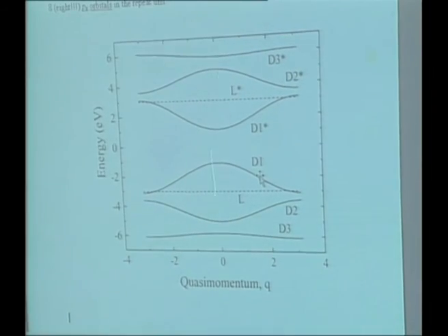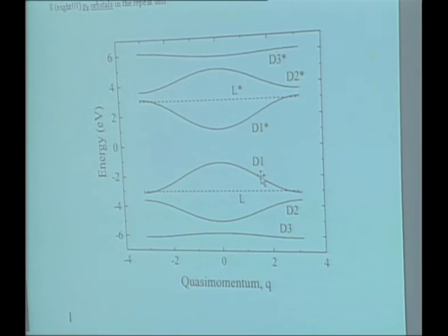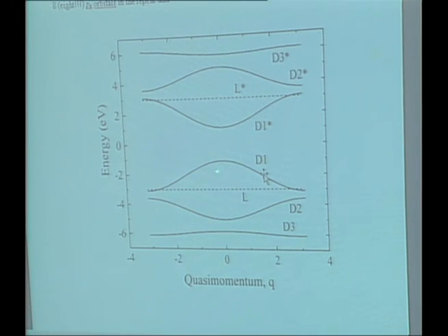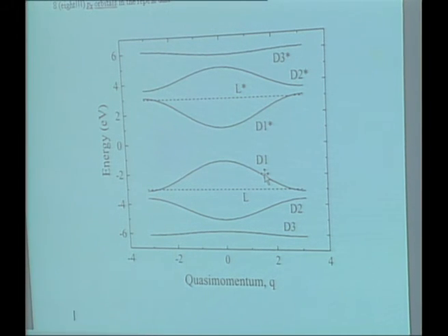These are broadband systems. There's a lot of polarizability here. If you calculate the dielectric constant, there's a lot of oscillator strength from this transition. Compare this with a polyethylene, for example, where all of this is gone. You just have sigma, sigma star. The dielectric constant is much smaller. The polarizability is much smaller.